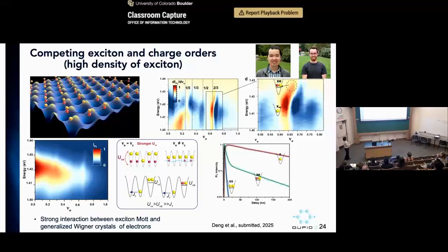In the same sample that I showed you, now I'm not just looking at excitons, but also at charges. This is photoluminescence as a function of doping into different densities of charge. What you see is that the exciton emission intensity changes quite abruptly at certain fractional fillings of charge, for example at 2/3 filling. This is well known, because excitons have been used for sensing charge orders. The reason excitons can sense that is because the dielectric screening changes when your charge crystallizes. When your charge is no longer moving around, the screening is much weaker compared to when it's moving around. So this is a pretty well-known thing already.